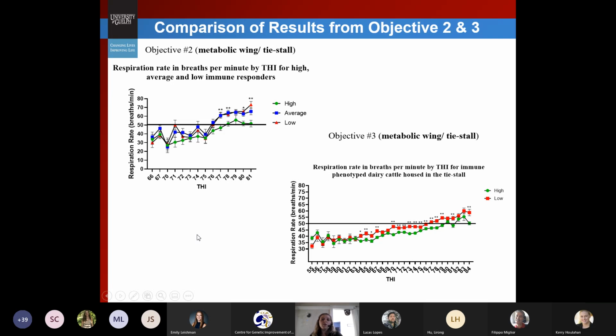So then comparing our results from that previous objective for the physiological mechanisms, these first graphs show what we found for respiration rate. Again, we're seeing a significant difference in the phenotypes, with the high immune responders having lower respiration rates as we get out to the higher THI values. And similarly, in the two studies, we saw for our lows and our average, the respiration rate going above normal in that THI range of 76 to 77, versus our highs not having respiration rates above normal until we get out to THIs of between 78 to 80.